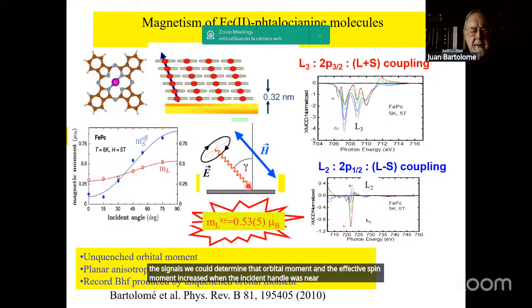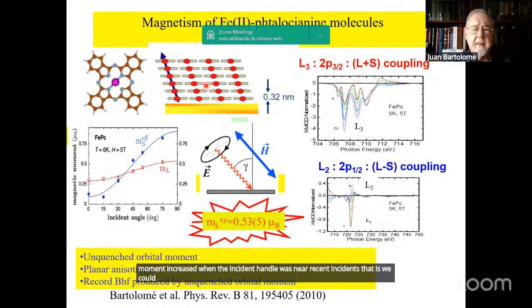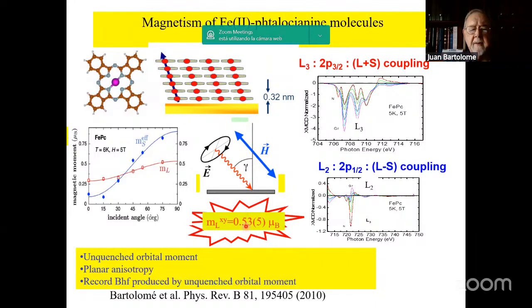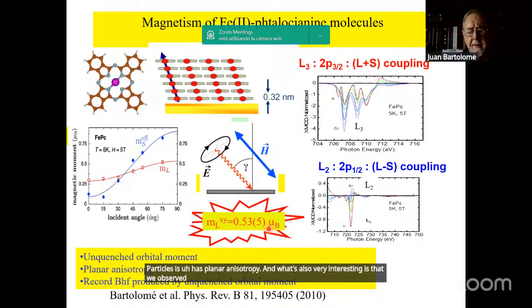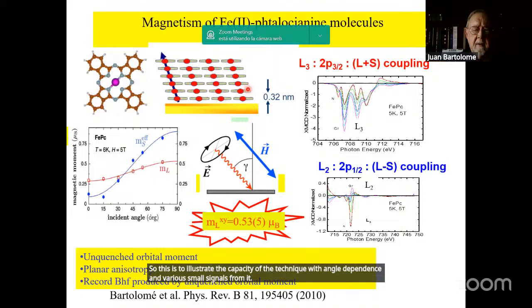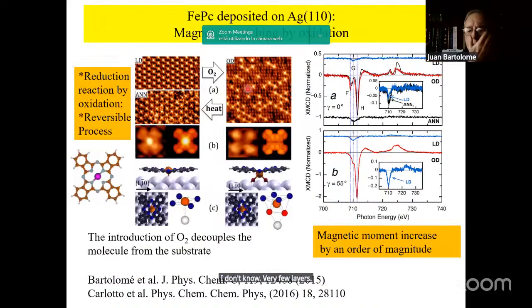grazing incidence. That is, we could prove that the magnetism of these phthalocyanine particles has planar anisotropy. And what's also very interesting is that we observed an orbital moment in the plane which is very high, which is clearly an unquenched orbital moment, which was quite unexpected. So this is to illustrate the capacity of the technique with angle dependence and very small signals from very thin layers. This is an extreme case.